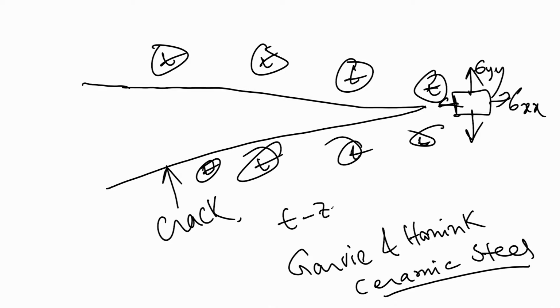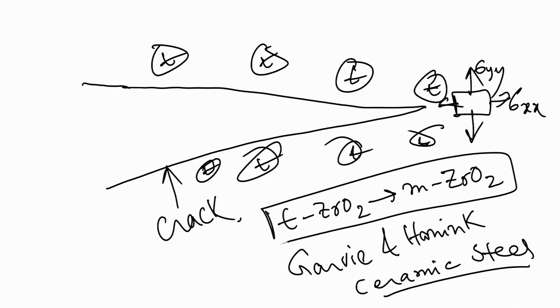I am just trying to explain you, tetragonal zirconia has always a desire to transform to monoclinic zirconia phase. Now, if tetragonal zirconia transforms to monoclinic zirconia, typically there is a volume expansion of 4 to 5%. So, 4 to 5% volume expansion, what it does, it will induce the compressive stress on the crack tip, and if these compressive stresses are realized at the crack tip, then what will happen?